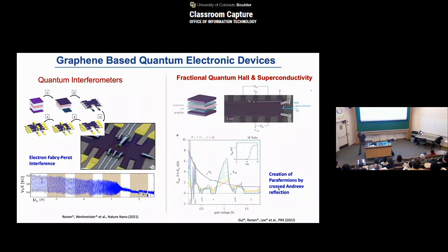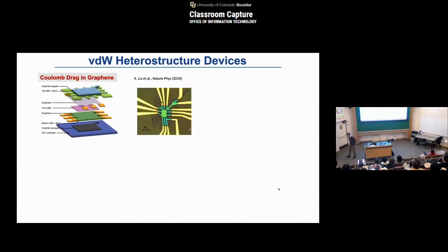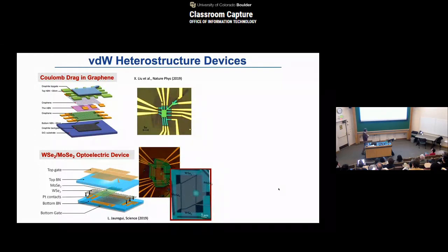Of course, we don't have to dwell on just one layer. You can put together rather complicated device structures, such as these two graphene layers separated by thin boron nitride, where each of the graphene layers is separately contacted and controlled by all the gate structures. This is a common device structure, and one can also build up with a few more layers stacked there. We can repeat this not only with graphene, but also, as I said, with other 2D materials.